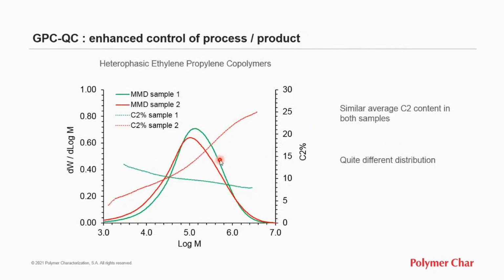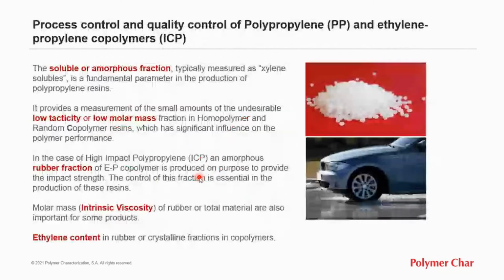Yet another application for GPC-QC may be found in the production of complex ethylene-propylene copolymers, measuring the molar mass distribution, but also the ethylene content is important to control. However, for the production of polypropylene, the so-called xylene solubles is a fundamental parameter. It provides a measurement of the small amounts of undesirable low tacticity or low molar mass fraction in homopolymer and random copolymer resins, which has a significant influence in polymer performance.